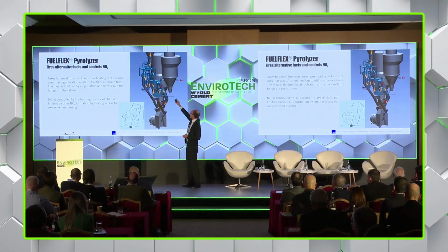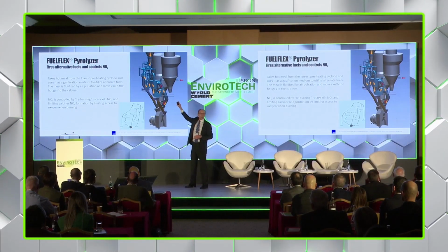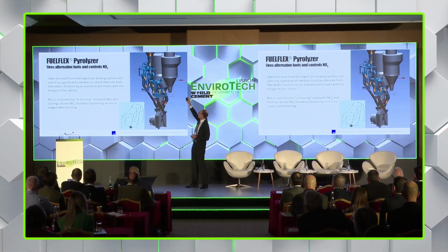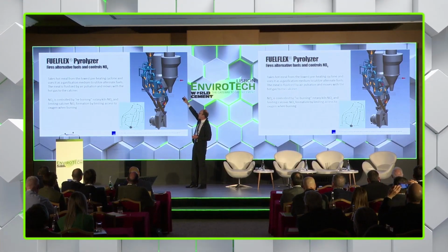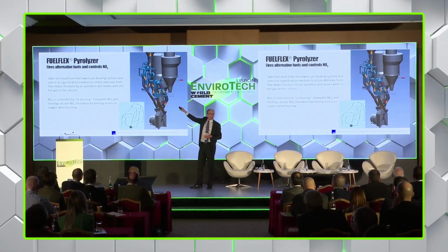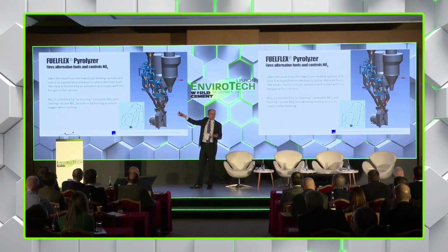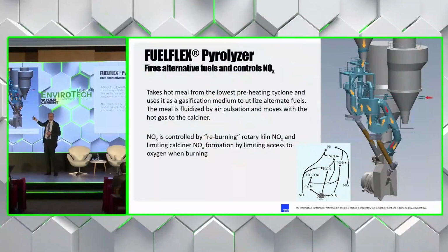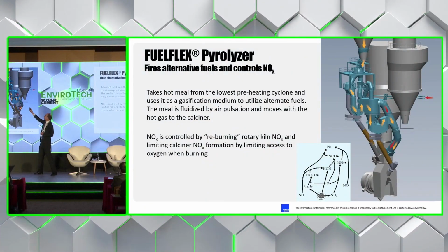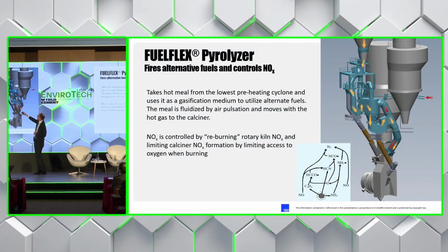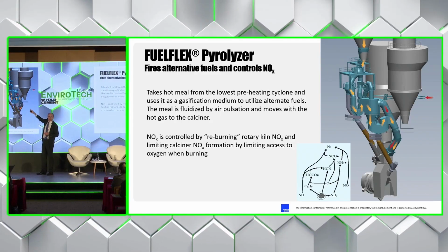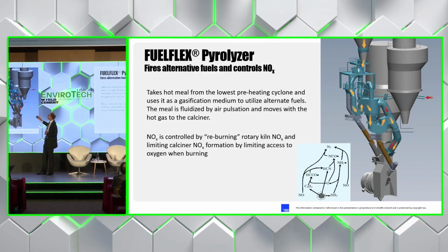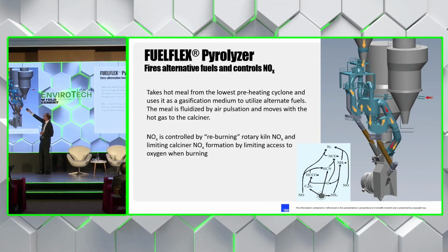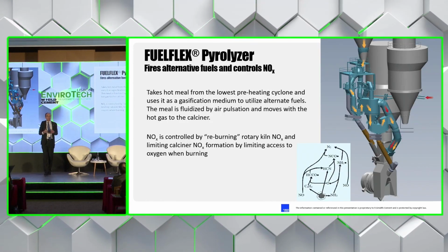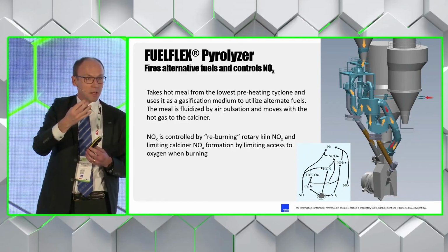The way it works is that we take hot meal at about 800 degrees Celsius from the lowest preheater cyclone. We then take it through two dividing gates. The first one conventionally divides the meal between the calciner and the kiln riser. With the second one, we can then divert it into the FUELFLEX Pyrolyzer, which is basically the blue unit you see up here. The meal flows first into what we call the U-lock, and this basically prevents the combustible gases from flowing backwards into the process.